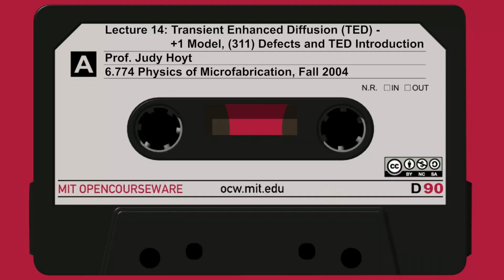So let's take a look at the inset up here. The inset shows schematically the initial epitaxial structure of this bipolar transistor. There's a region on the bottom in depth, which is N- silicon. And then there's a region that is P+, so it's got a high amount of boron, silicon germanium. And then there's some lightly doped region. And then there's an N- silicon cap. So if you look at the SIMS data, boron versus depth, the region down here marked silicon, that's all epitaxial silicon.